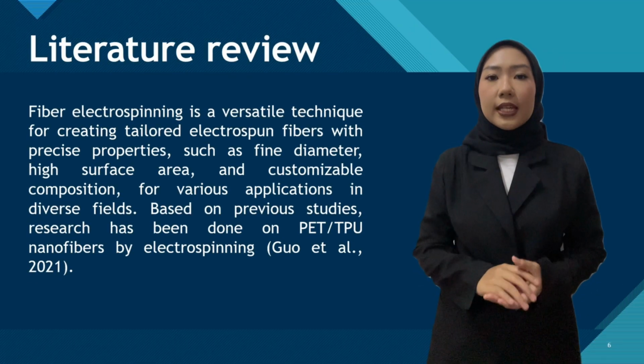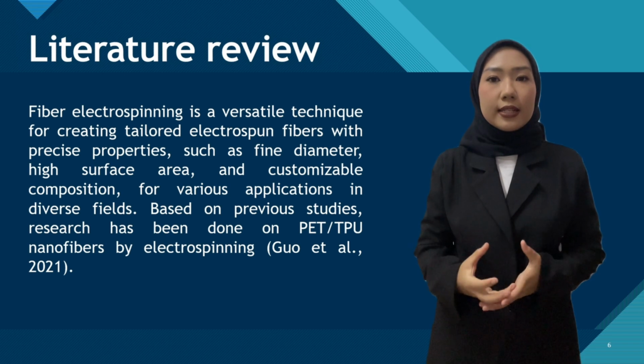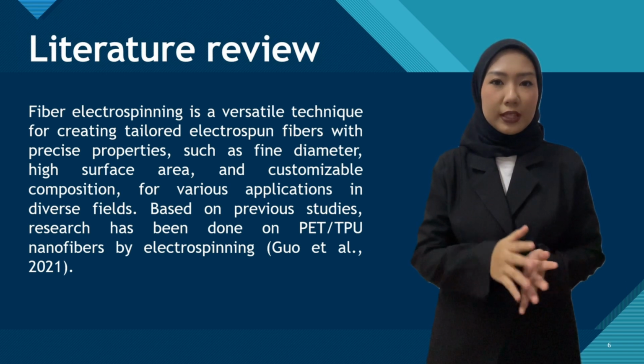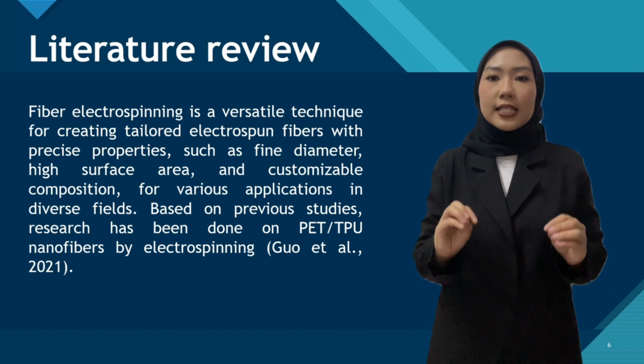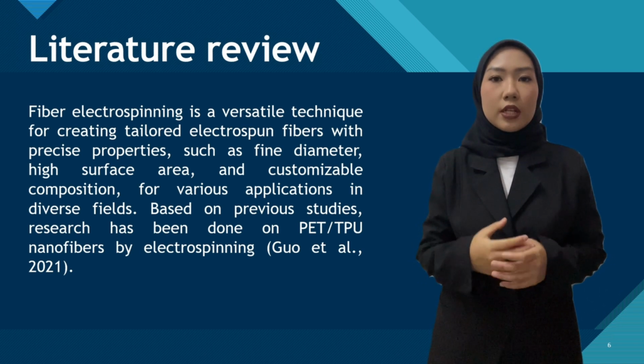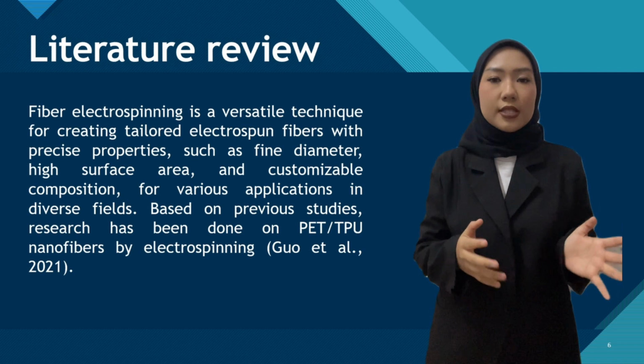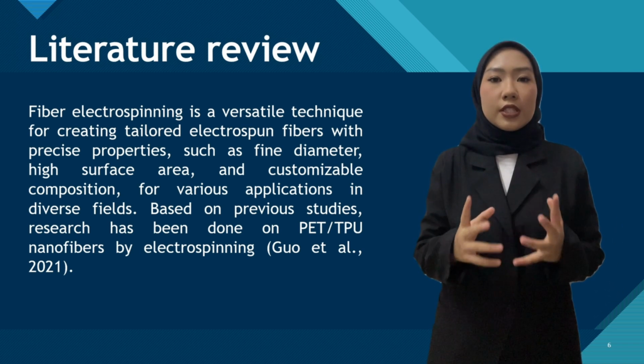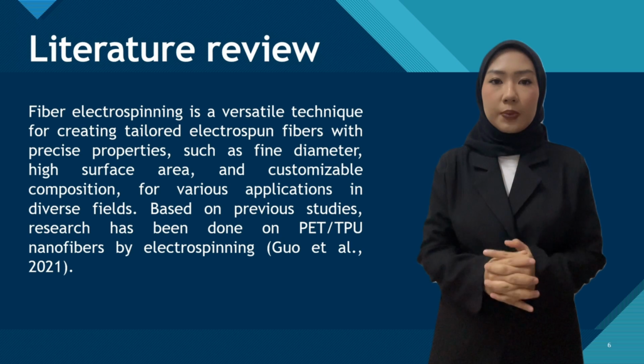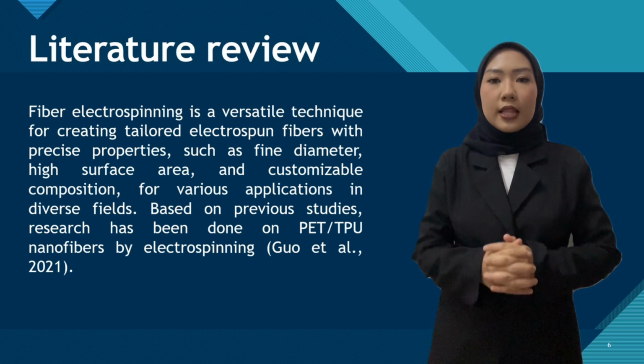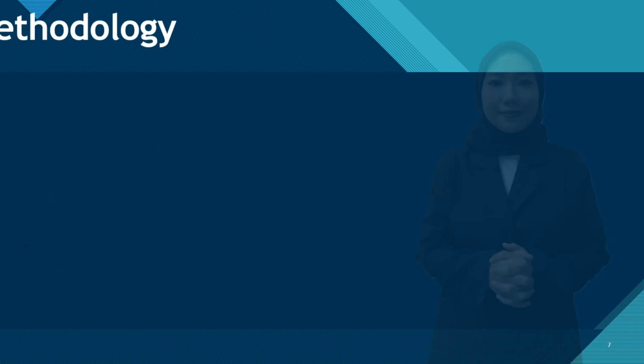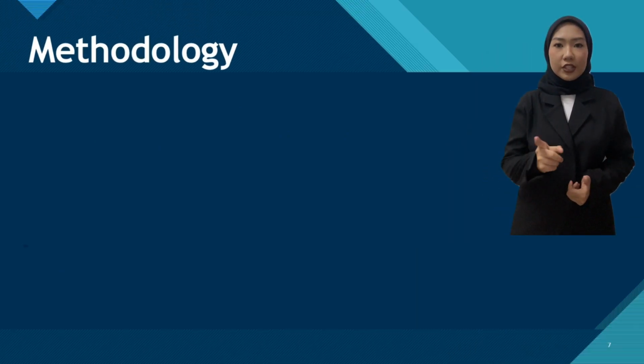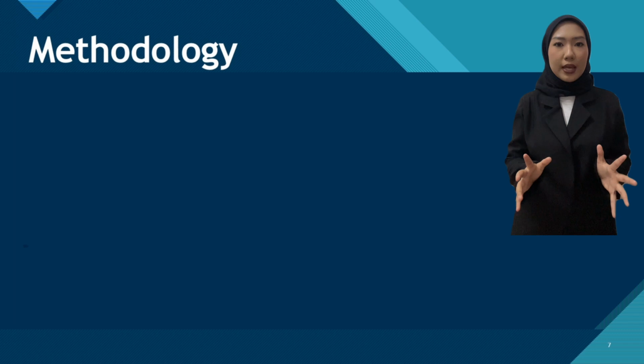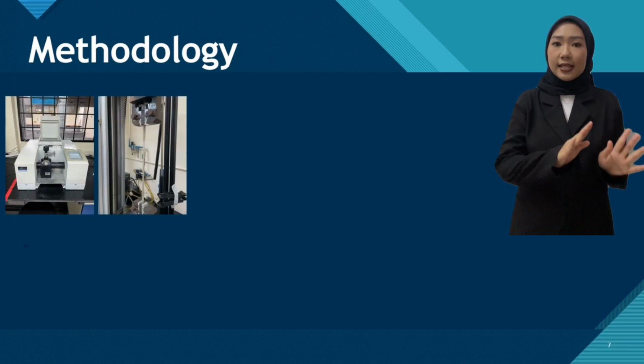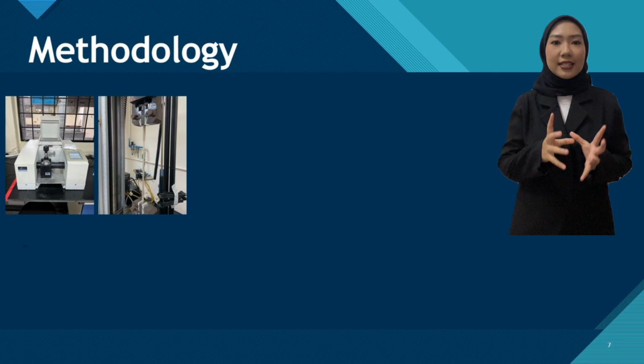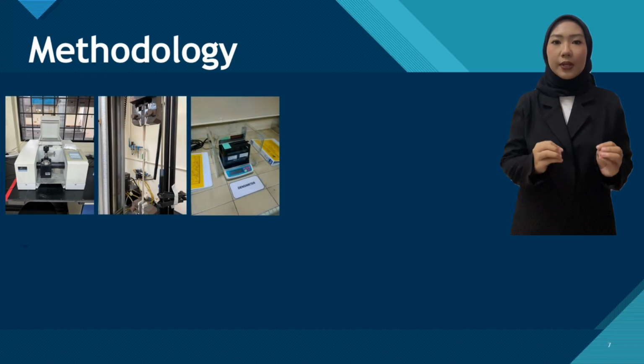Fiber electrospinning is a versatile technique for creating tailored electrospun fibers with precise properties such as fine diameter, high surface area, and customizable composition for various applications in diverse fields. Based on previous studies, research has been done on PET and TPU nanofibers by electrospinning by Guo 2021. Before electrospinning, the characterization of recycled LDPE and EPS began with FTIR, then a tensile strength test using an Instron tensile testing machine, then a density test using a densimeter.